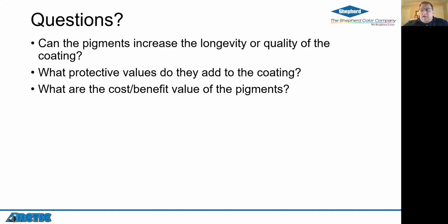What are the cost benefits of the value of the pigments? Definitely, you can expand into new marketplaces. With a lot of building products, you almost have to use cool materials in them right now. The other thing is that the Arctic reflective pigments are on par with the other standard high performance pigments in cost. If you're coming from a carbon black based coating, carbon black has a much lower density than these IR reflective pigments, and the use rate is much lower. So when you go from a standard carbon black pigmented coating to an infrared reflecting black coating, you really have to change a lot of the pigmentation parameters.